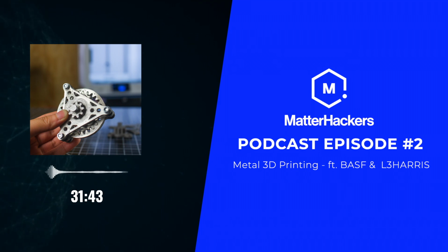So once we get all that done in the manufacturing preparation, then we do the 3D printing. Of course, again, it generates the green part size, and we slice the file, generate the G-code program. Again, the parameters are a good place to start that BASF has developed. We're finding that keeping the material dry is very helpful. It doesn't have to be, though, but we do keep ours dry, and we keep our humidity controlled in the printer, mainly inside the printer. We've found that a heated chamber does help a little bit, especially on tall parts, for uniform layer thickness. Next slide.